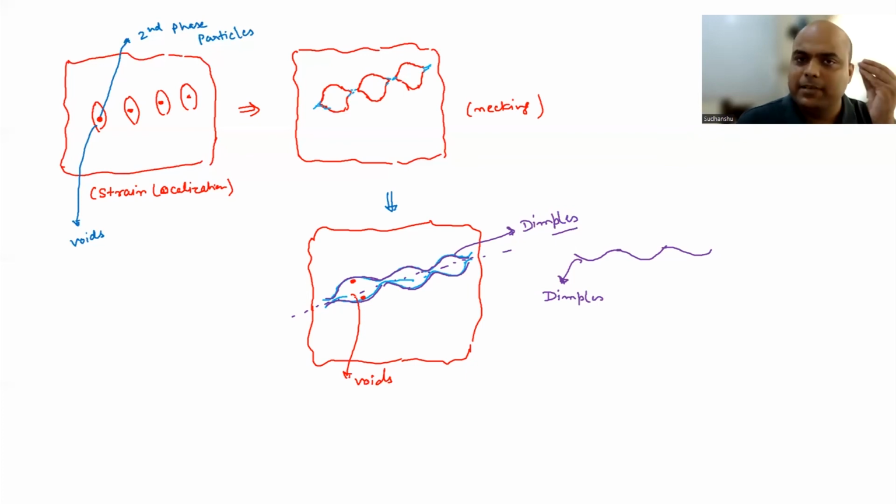These particles can be small or larger, but they will be there. And on both sides you are going to see dimples because of this. So I hope you have understood how dimples are forming. Here, these are uniform size dimples. Why? Because the particle size is uniform. They are going to nucleate and grow together, so you are going to see dimples of almost uniform size.